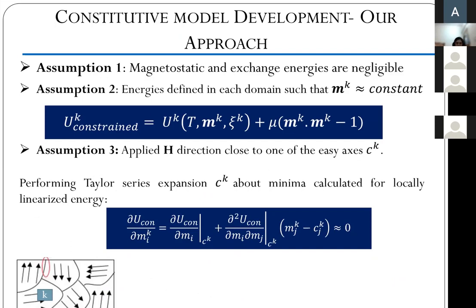We solved it using this approach, and we compared it with the approach that we used in our group, which was to locally linearize the free energy about each easy axis. So what we did was take the free energy term, define it within each domain, and do an expansion about the easy axis. For linear response, the free energy has to be of quadratic order, right? So we take the Taylor series expansion up to quadratic order, and we keep the constraint.